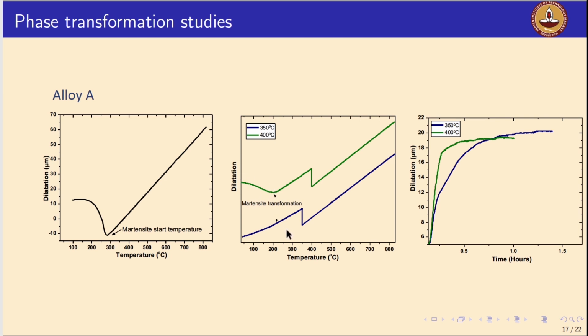Right. The other important criterion when we are carrying out the dilatometry analysis is that we also look at the time of transformation. So we cannot keep on holding the weld for infinite time, right? We'll have to achieve a complete bainite transformation in a shorter duration, so that the weld can be taken out or the next pass can be deposited.